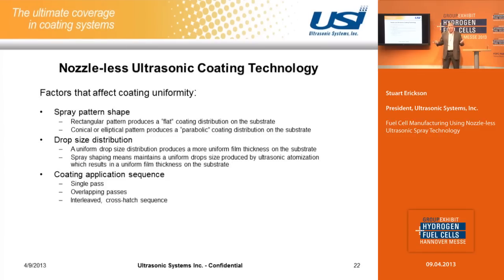So when you have a coating device and you have a substrate to coat, there are many different ways of applying the coating, what we call the coating recipe. One way is to apply a single pass, which means a series of spray applications right next to each other, and try to make a uniform coating that way. Another way is to overlap the coating application. So if the width of your spray pattern is 100 millimeters, maybe you take a pass every 50 millimeters. Or another one, which is what we typically do with the fuel cell, is to interleave the patterns and also do a crosshatch, and you'll see an example of that.